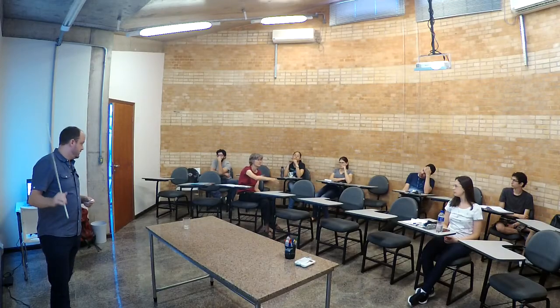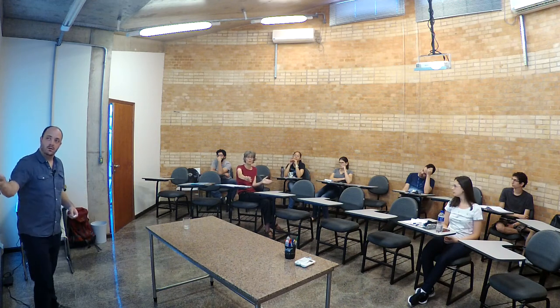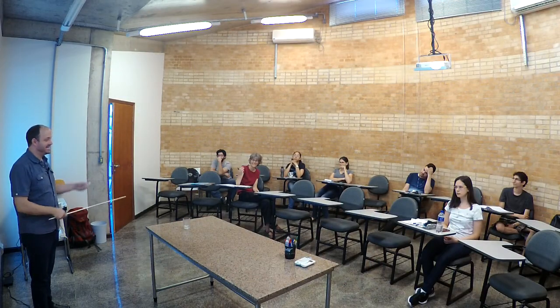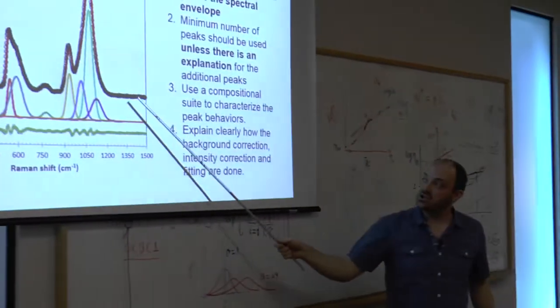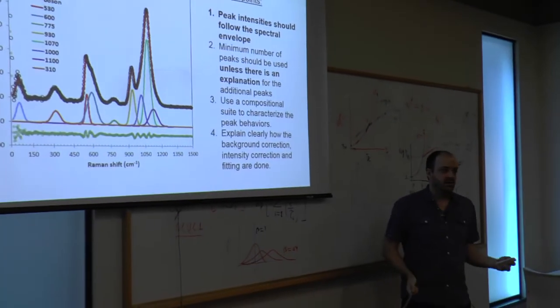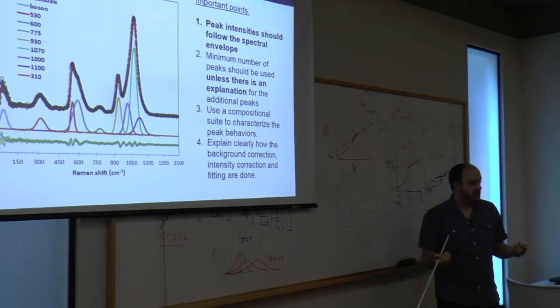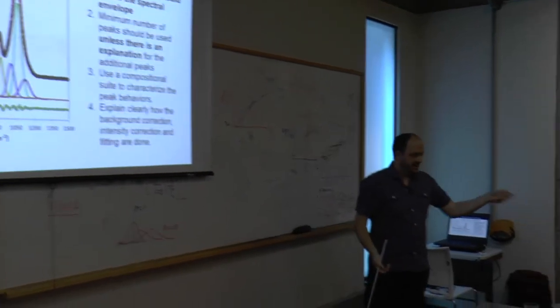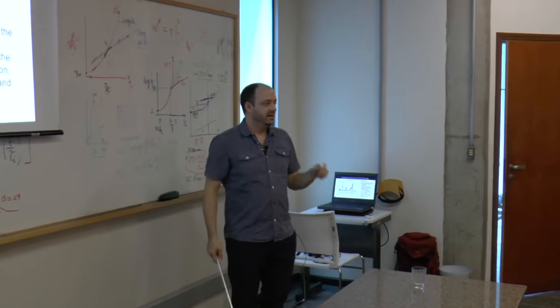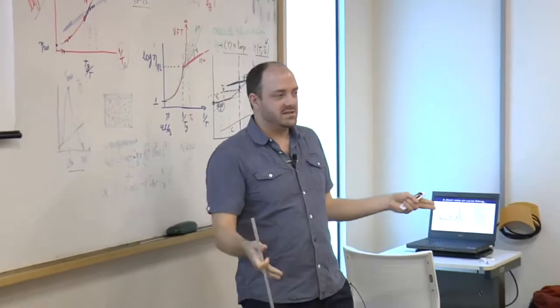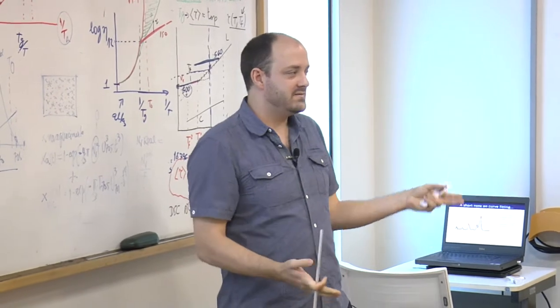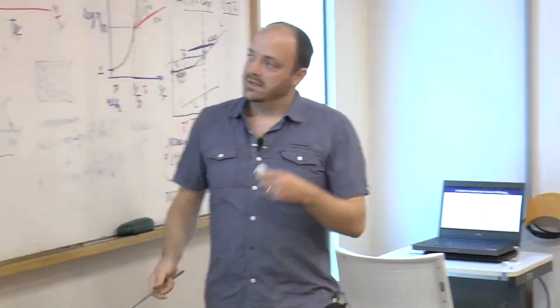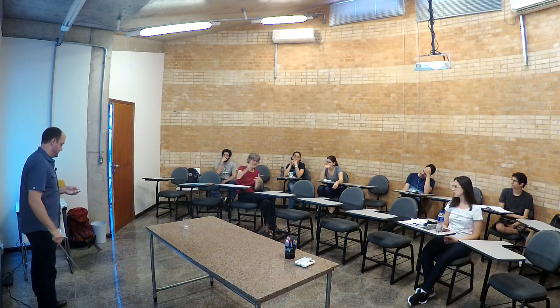And if you have a glass series of 10 glasses with composition or temperature or anything. The best way is to look at a glass compositional suite to see how the bands shift as you add these modifiers and other features. That'll give you an indication of where new bands pop up. Use a consistent fit the whole way through. If you just decide to change your fit at 50% silica and have one series fit for one and another series fit for the other, probably your model is not so good. You might have to fit the same 10 glasses 5 times until you have one set of fits that fits all 10 glasses, then you have to do it 5 times.